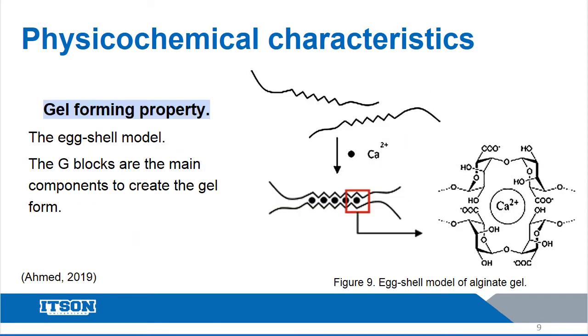One of the main characteristics known about alginate is that it can form gels. This is thanks to their interaction with some cations, undergoing ionic gelation through the cross-linking process between different chains of the polymer, meaning that they get linked together like we can see in the picture. And this part is the egg-box model because it looks like one.